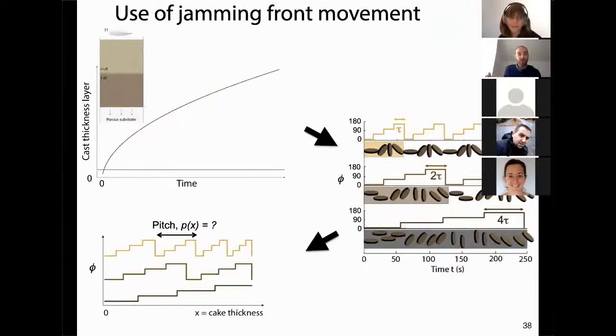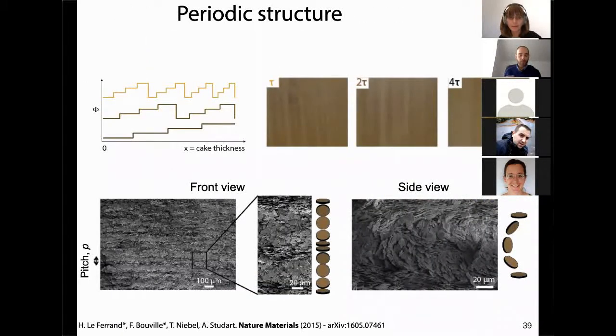So the question is, how do we reproduce this type of sample again? Well, if you remember, if you take slip casting, we know how to predict where the position of this cake layer is going to be over time. And the platelets here are still free to move. So we can change the orientation of our magnetic field over time, and hopefully we will see a change in orientation of our particles, and again try to make the same microstructure in the end. And that's what we observe.